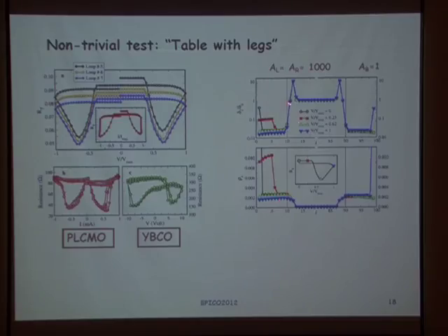So, for example, if we concentrate on this left-hand interface, we start at zero voltage. We have this initial vacancy density profile, which is the black one. As we increase the voltage, the density of vacancies decreases here, and with the positive voltage, we put vacancies on the bulk side of the interface. So as we increase the voltage, we extract vacancies from this interface and put them on the bulk side of the interface. The same happens at the right-hand interface.